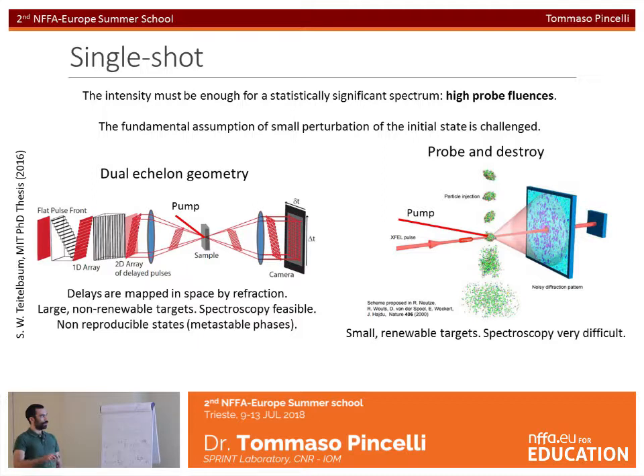So the two approaches are the dual echelon geometry, in which by making a flat pulse front cross wedge-shaped optics, we create a two-dimensional set of delays. So for each pixel of the camera, we have a different delay. And then in a single shot, we acquire all delays. So we pump the system and we look at all delays spread on the camera. So this is useful for large non-renewable targets and makes spectroscopy feasible because it uses relatively low intensity pulses, and it can map non-reproducible states, such as sending the system into a metastable phase.